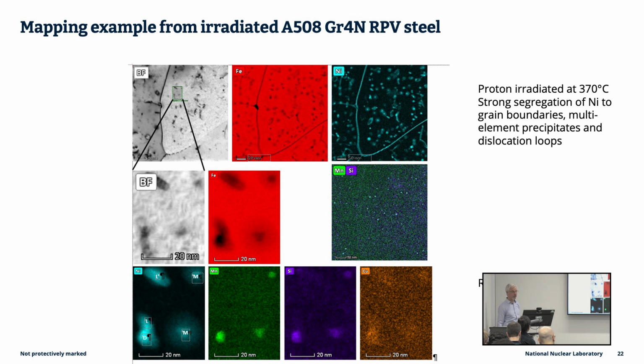In my experience, it's not that great, except obviously if you're looking at something daft like a twin, which isn't a grain boundary anyway, and you should be able to spot that. Alex also did some really great mapping on these radiation-induced clusters, which tend towards two sorts of types really. There's the manganese nickel silicon G phase, which is a late blooming phase at high doses in irradiated pressure vessel steels, and also the nickel segregation to dislocation loops in these two locations here. And the spatial resolution in these maps is really excellent.